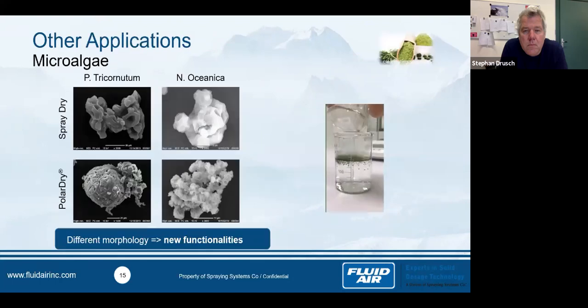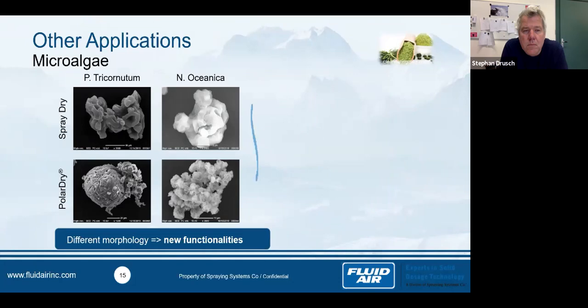So it's the powder that you obtain. You can see we have a wettability that you can see on the right. And also we did some SEM pictures. The first thing that you can observe is we can increase the particle size. It was possible to agglomerate particles, and in this study we increased by between 2 and 3.